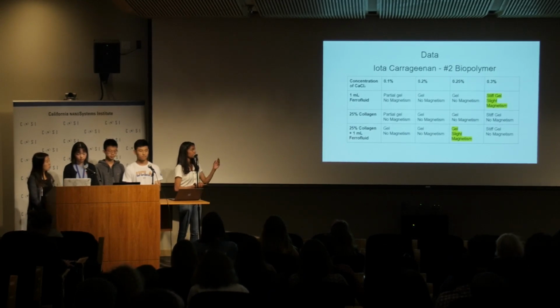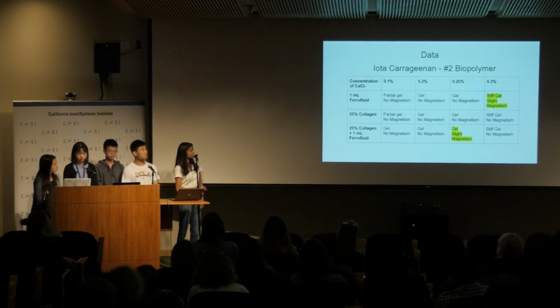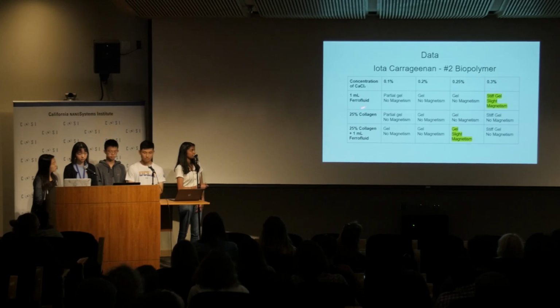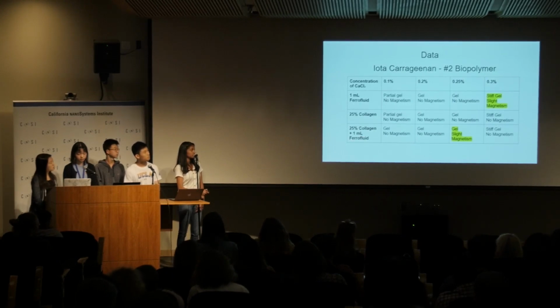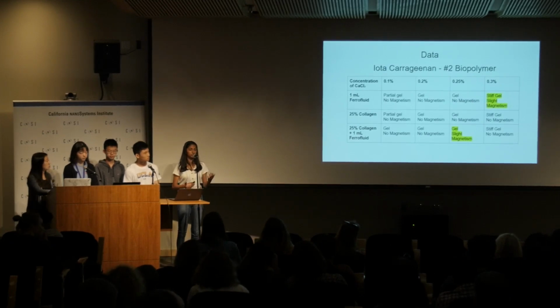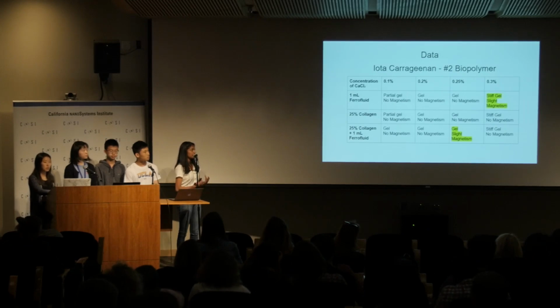So we had 3 variables for the concentrations. First was just ferrofluid, and we did that for every concentration of CaCl2. Then we had one with 25% collagen, and then one that combined both of them. Highlighted, you could see the ones that we found most ideal, which had a balance between the solid and liquid states of matter and had slight magnetism.